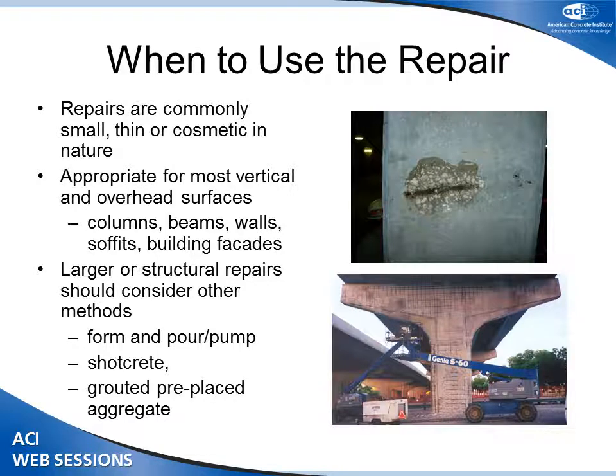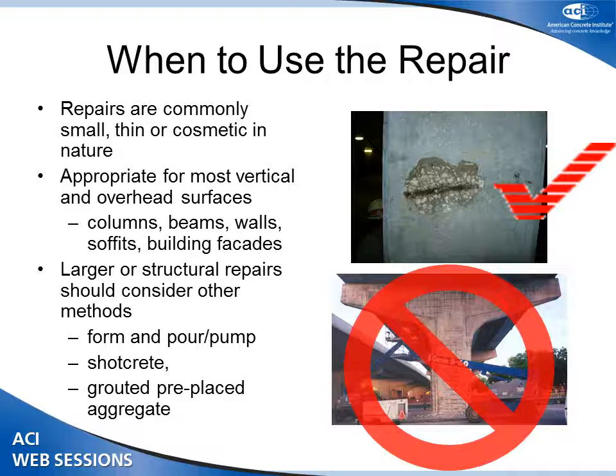So as I said, when do you use this type of method? The repairs are commonly small, thin, or cosmetic in nature. It is a vertical and overhead repair method. So you're looking at using columns, beams, anything with a vertical or overhead orientation. If you do have larger repairs to complete and more structural in nature, this would probably not be the preferred method of repair. For one reason, it's more labor intensive than some of the other methods. But the other methods can get better consolidation and more structural repair materials into the repair itself. So, for example, on the photographs on the right, you see that the repair on the top may be a good application, but the repair on the bottom, where you see widespread repairs, this project was actually completed using a shotcrete method.